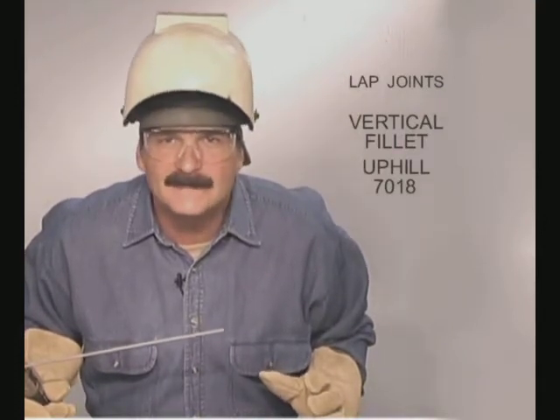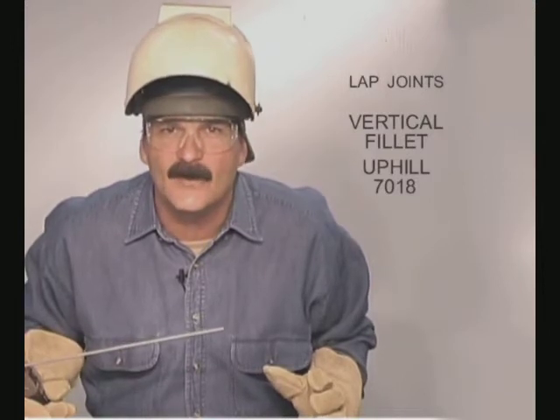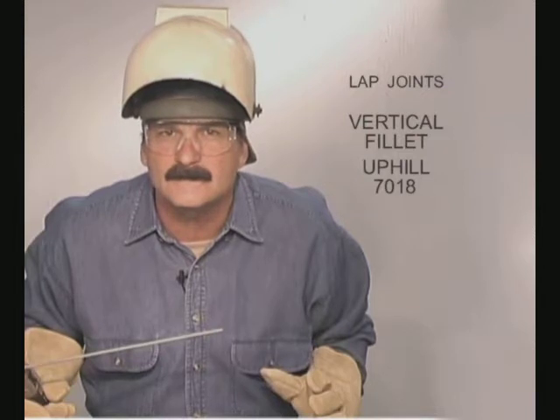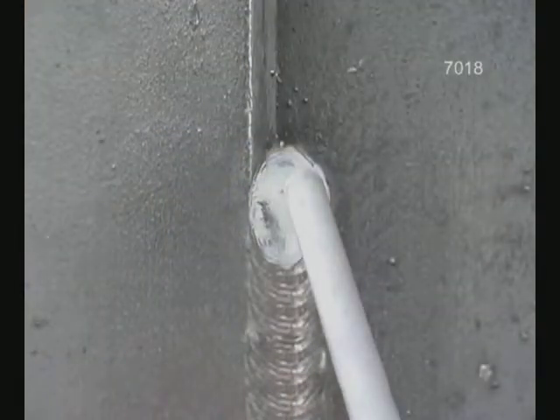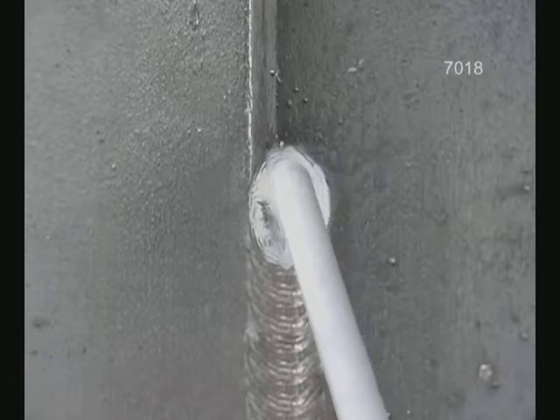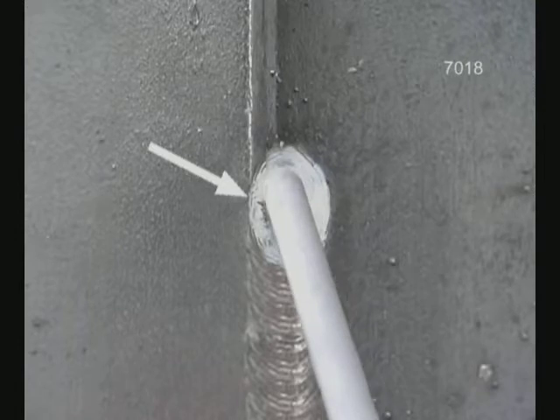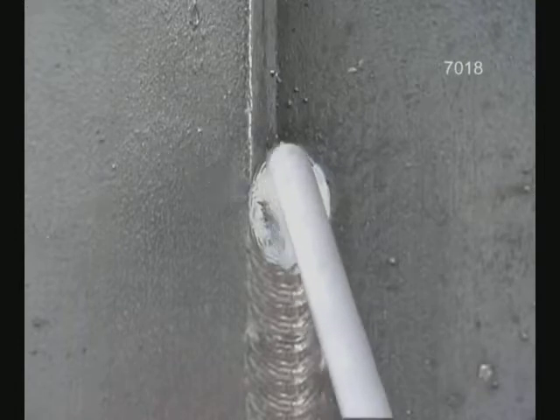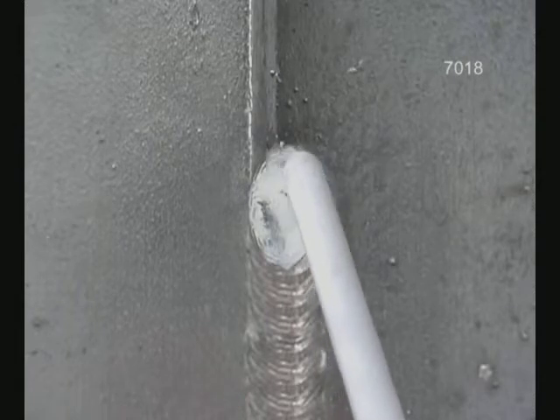Always keep in mind that 70-18 is very sensitive to the arc gap. You don't want to jam the rods into the sides or long arc across the center. Carry the heat on the back piece. As soon as the puddle flows out, move into the corner, letting the filler metal flow to the outside edge, even pulling the rod out a little if necessary to maintain a uniform arc gap. Then back into the corner and across, slowing down to let the puddle flow out.